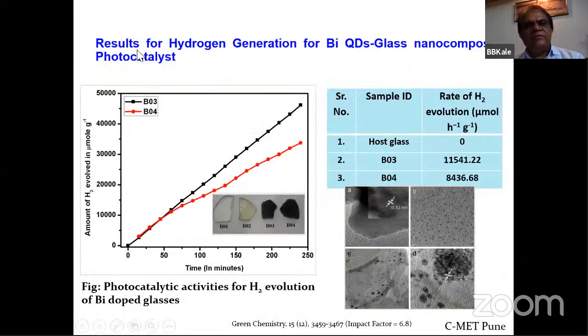Then a very typical example I will show you for hydrogen is when you have bismuth nanoparticles in glass. Why do we use bismuth nanoparticles in glass? Because they cover the whole spectrum of solar light and absorb the sunlight, and because of that you get a huge amount of hydrogen. We used this glass as a catalyst for the first time. We have a US patent on this.